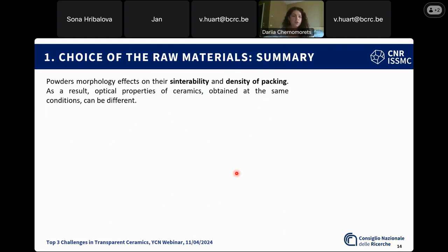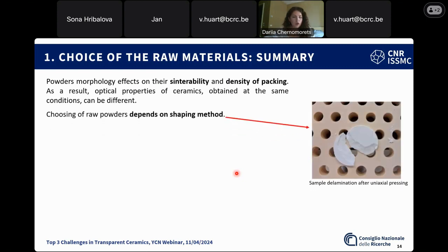Regarding downsides, there is possible formation of secondary phases. It is also quite possible that deterioration of characteristics of the laser source or scintillator can be observed, and parasitic absorption can appear, visible as coloration. In this case, annealing is needed.